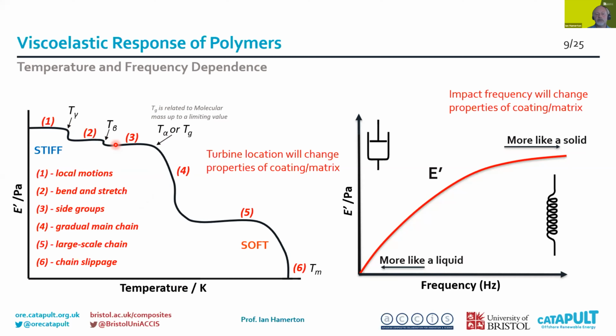over one another. So each of those has quite a profound effect on the mechanical properties, such that material can be quite stiff at certain low temperatures, and become quite soft and compliant as the temperature increases. So the key point here is that turbine location will change the properties of the coating in the matrix. So we have to be very, very aware that a test needs to be performed at an appropriate temperature that reflects the use temperature. Similarly, if we look at the frequency of impact, then as we apply a load, again, the modulus changes such that the material may have more fluid-like features at low frequencies, represented here by a dashpot, whereas the material may perform more like a solid, less like a Newtonian fluid, as the frequency of impacts increases.